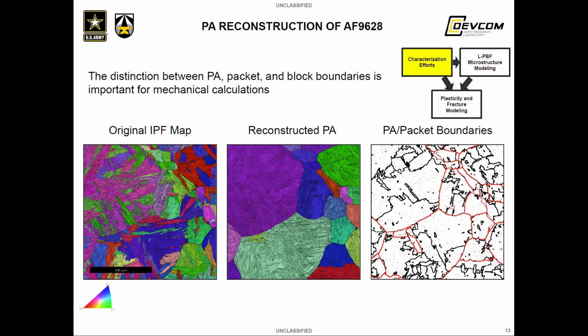This boundary map illustrates the relationship between austenite texture, grain size, and final martensitic grain boundary structures. And this information is invaluable to the modeling of the plastic behavior in this material, since it's the grain boundary structures that greatly define strength and hardening behaviors.